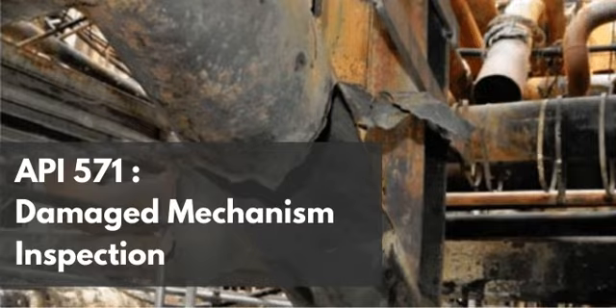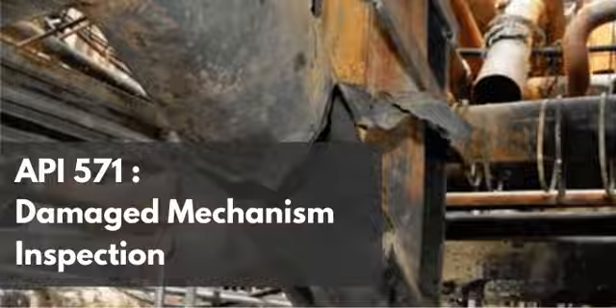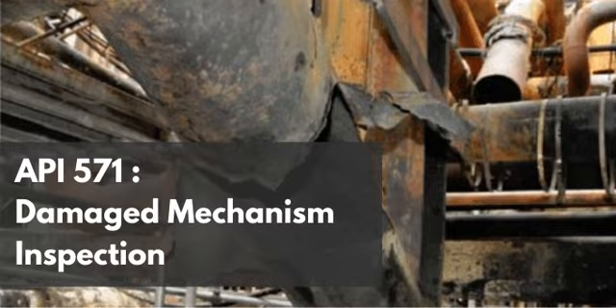An oxide layer is essentially a highly controlled layer of good rust. But in this extreme high temperature context, we are talking about highly specialized, tightly adherent oxides like chromium oxide or aluminum oxide. These specific oxide molecules form a dense, completely continuous, impenetrable ceramic barrier right on the exact surface of the underlying metal. So it's like a ceramic skin. Yes. The molecular bonds holding this ceramic layer together are incredibly strong, and the atomic spacing is incredibly tight. The carbon atoms in the high-temperature gas phase simply cannot penetrate or diffuse through a continuous, stable oxide layer.